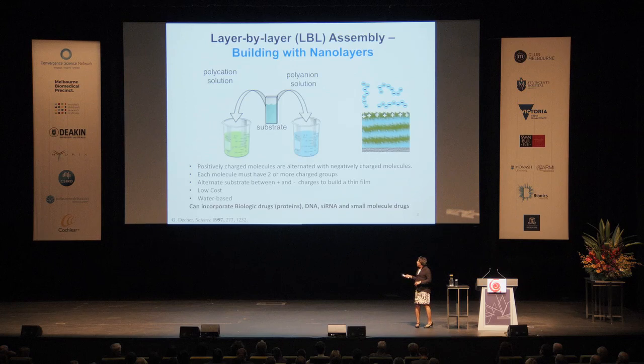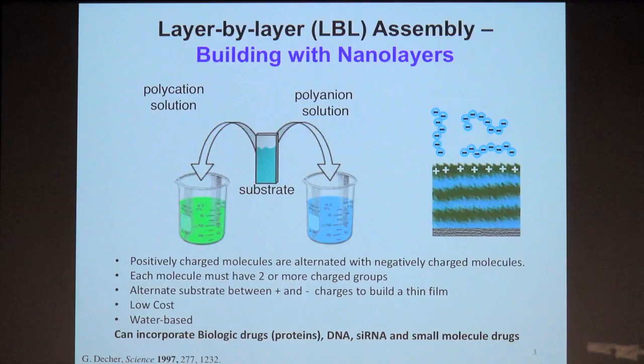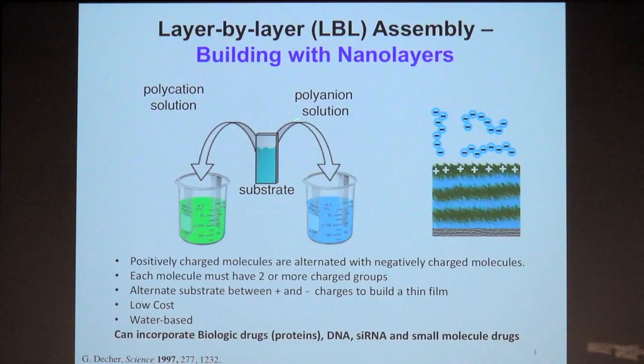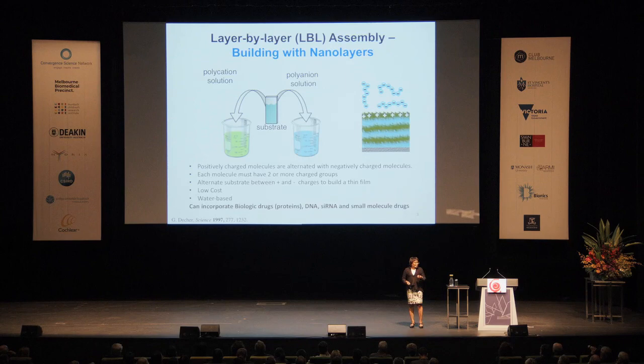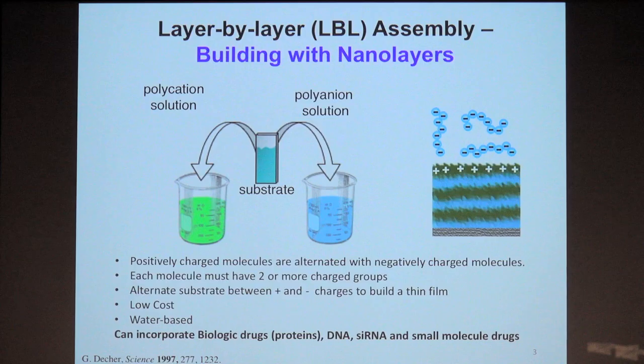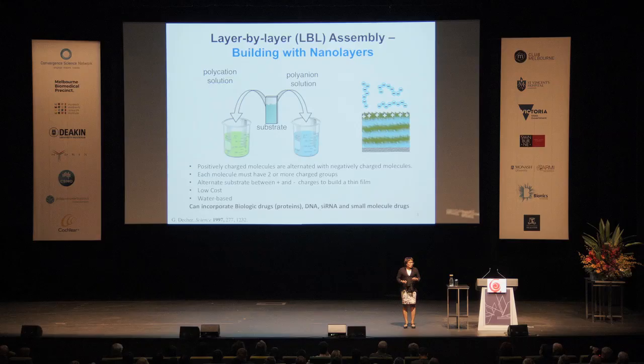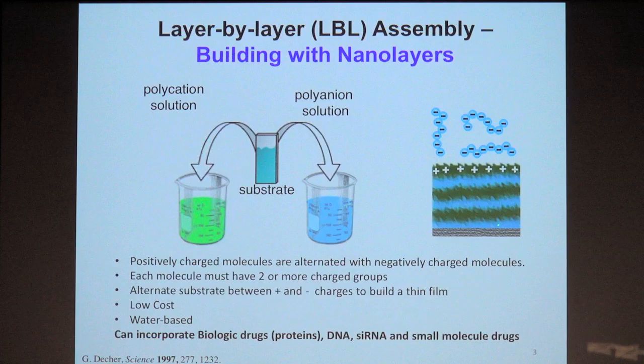You can only adsorb to the point where you reverse the charge, we create our monolayer, our singular layer. That layer can be anywhere from 1 or 2 nanometers thick to a few tens of nanometers thick, depending on what we're adsorbing and the conditions that we adsorb at. We can then rinse the substrate and immerse it into another water solution that contains something that is once again oppositely charged, negatively charged, and adsorb back and forth. And you can imagine as you go from plus to minus to plus to minus, as long as you have a rinse step in between to remove anything that's not truly adsorbed electrostatically to the surface, you're going to build up a stable film. Now, I'm showing these as alternating stripes because it's easier to see that way.